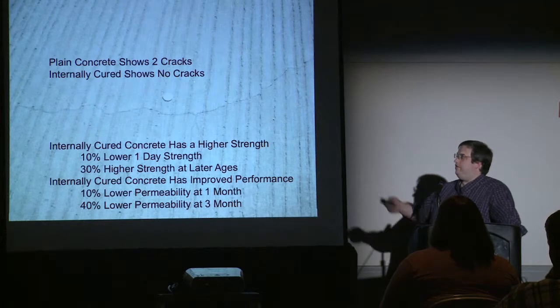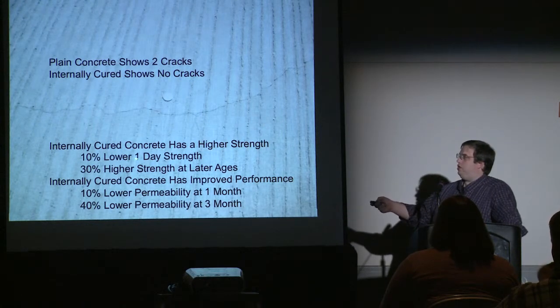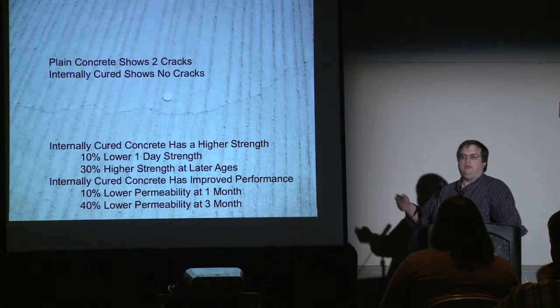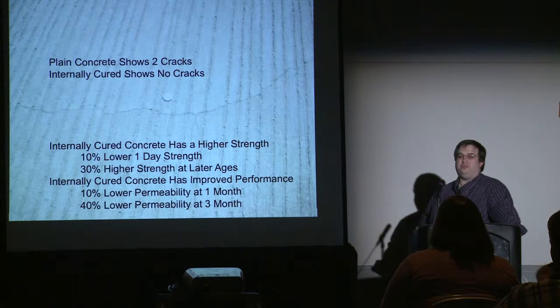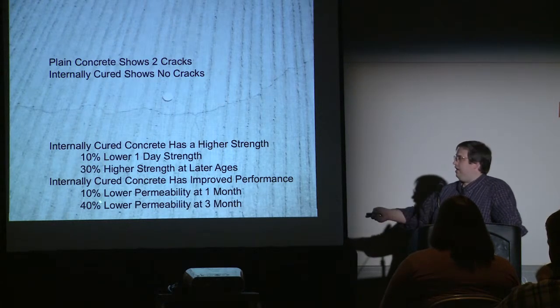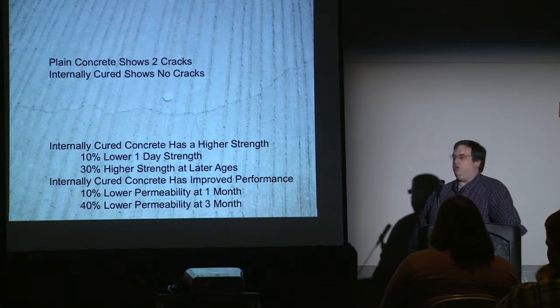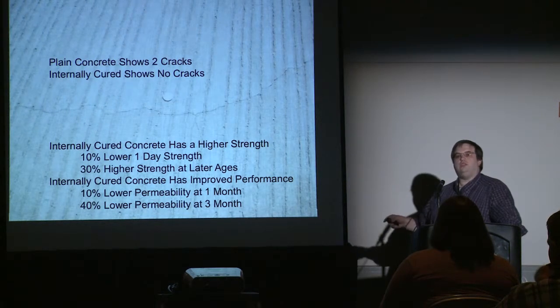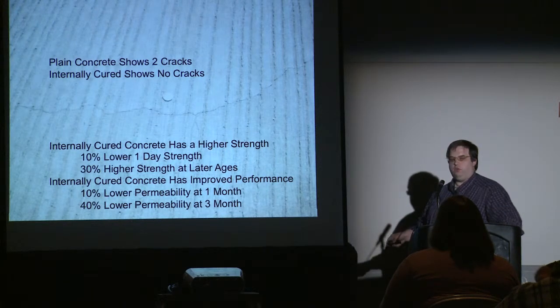In addition to not having cracks, the internally cured one had about a 10% lower strength at one day, but it had 30% increase in strength as we went on. By about 3 to 5 days, they had equivalent strengths. The internally cured concrete had 10% lower permeability at 1 month and 40% lower permeability at 3 months. Lower permeability translates into it's going to take your chloride ions longer to get to the reinforcing steel. It's going to delay the corrosion of that reinforcing steel.